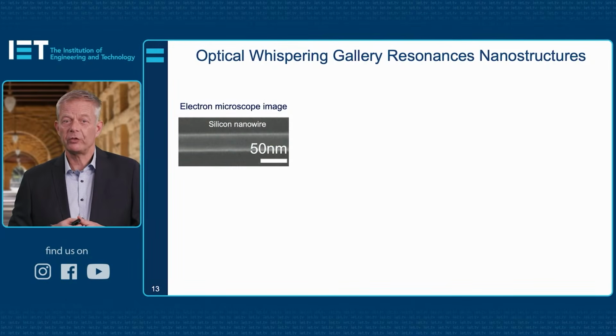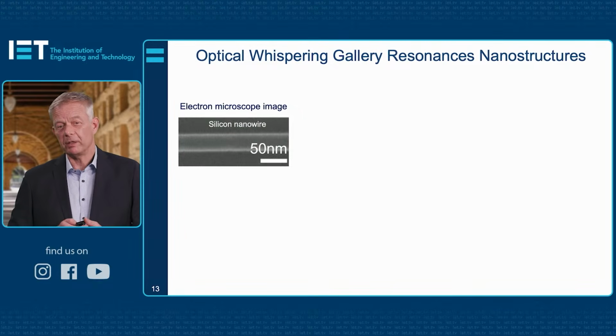Now, if one looks at the same thing, not for a microsphere, maybe the diameter of a hair, but something much smaller, a nanowire of semiconductor silicon, one can use the fact that silicon and other semiconductors can have much higher refractive indices, maybe 4, 5, or sometimes even 6. And if you have such a high index, even in a small structure that's just maybe 50 nanometers in diameter, so 1/10 of the wavelength of light in free space, light inside can still resonate.